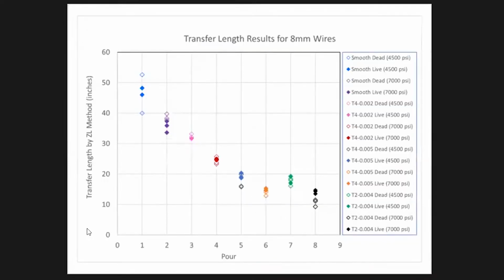Okay, so here are the results, and we'll look at correlations. With 8mm wire, the smooth wire at 4,500 PSI, we're seeing a transfer length value up around 48 inches. Obviously, that's not going to be any good for a railroad tie, right? But it's a baseline point. If we go from 4,500 to 7,000 PSI, now the transfer length comes down to around 38 inches. And here we go to the T4002, T4004, and then finally the T2 depth indent 004. And so you can get a transfer length here down around 13 inches with an 8mm wire, depending on what release strength and what depth we want.